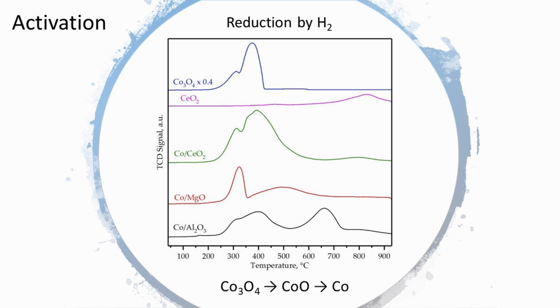different conditions. The relevance of this example is related to Fischer-Tropsch synthesis, for which metallic cobalt nanoparticles are active. Since cobalt oxide can form mixed compounds with oxidic supports, for example cobalt aluminate, cobalt silicates or cobalt titanates, their reducibility may be different.